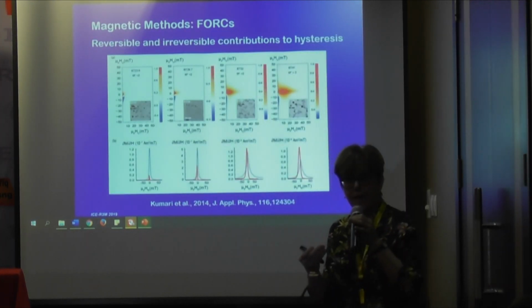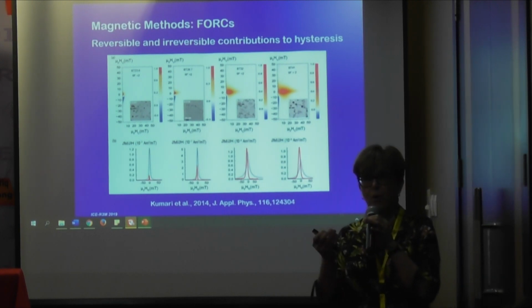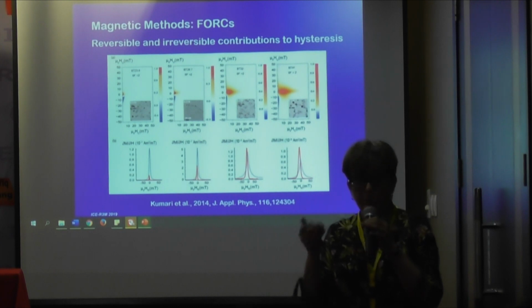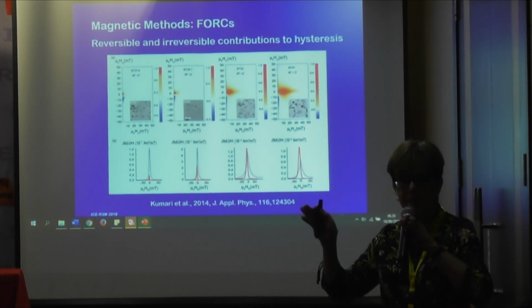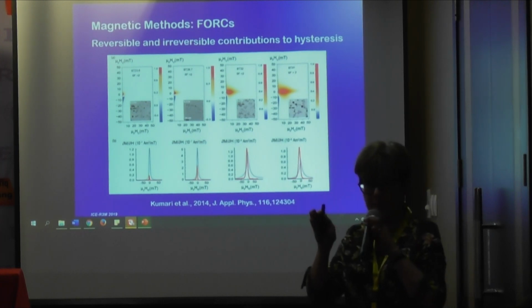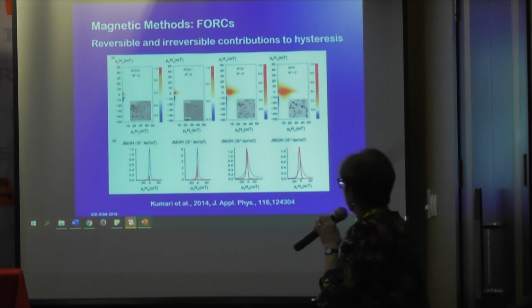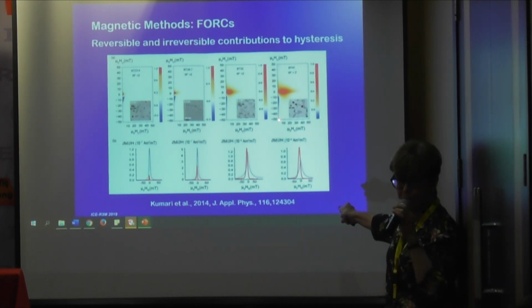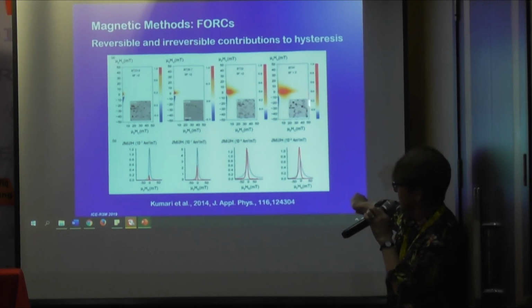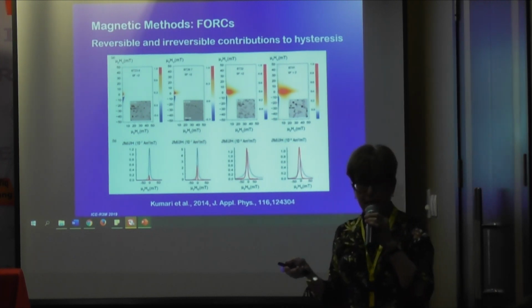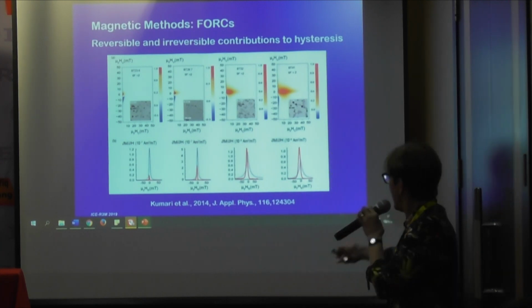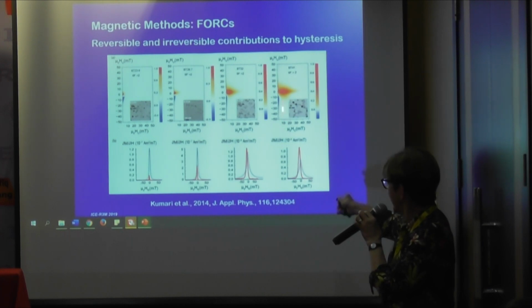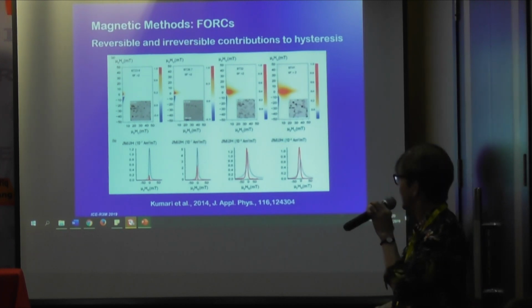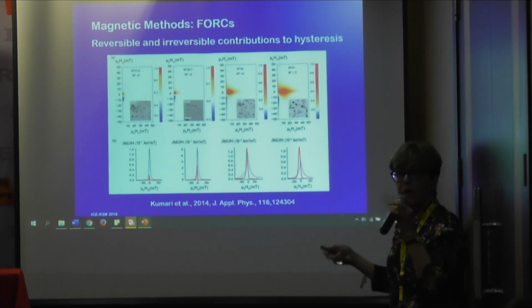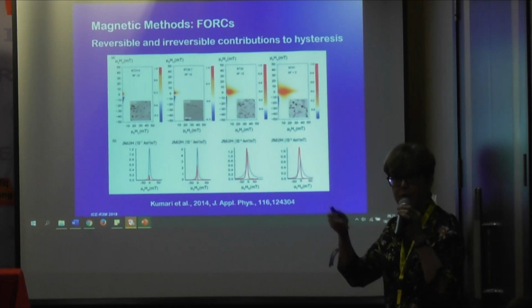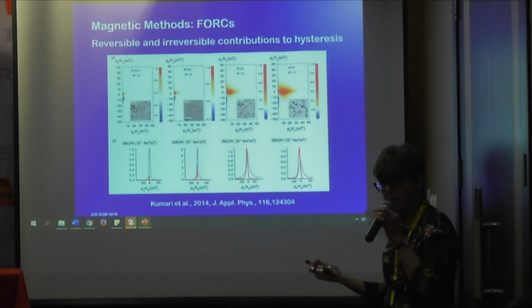Now there's more information you can get out of a FORC diagram. One thing you can get out is what part of my signal is irreversible, that means what is contributing to the open hysteresis loop, and what part of the material is reversible. So this is an example of magnetosomes from a bacteria. Most of the grains are above 25 nanometers, so they fall in the range of single domain. And you can see I get this nice FORC diagram here with an average coercivity of about 10 millitesla. For these kind of bacteria, they make a little bit wider grain size, so there are some finer grains under 25 nanometers and some larger grains over 25 nanometers.